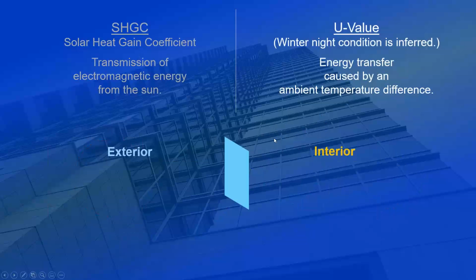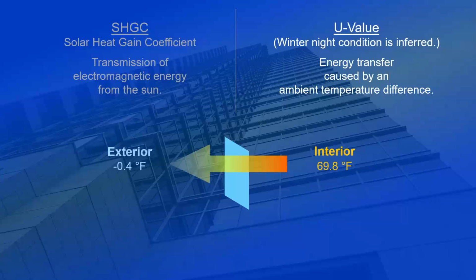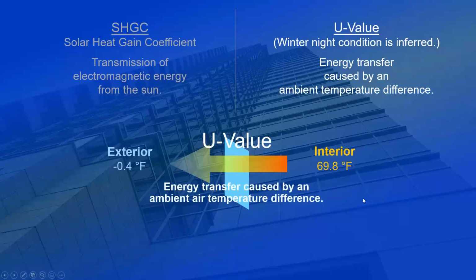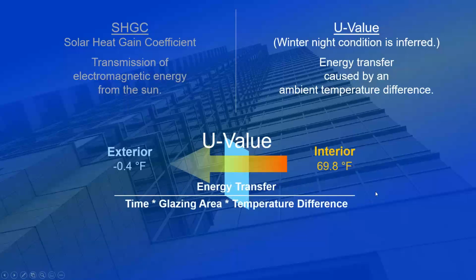A U value, again, is the energy transfer caused by an ambient temperature difference. A lower U value results in a higher R value. They're the inverse of each other. So for example, if you have a U value in BTUs of 0.25, you will have an R value of 4. A U value of 0.10 is an R value of 10. Energy transfer divided by time, glazing area, and temperature difference.